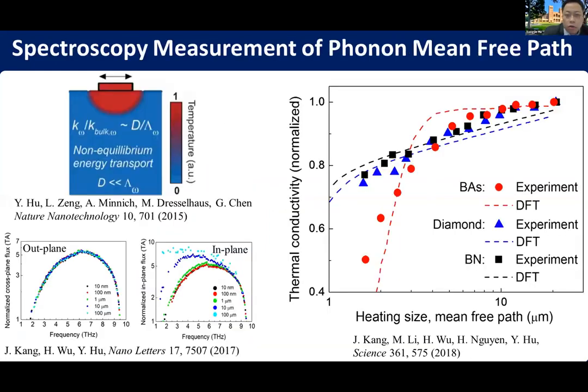We also performed spectroscopy measurement of phonon mean-free paths. So phonon mean-free path is a very important parameter that describes average distance for phonon to travel before it scatters. Usually, a longer phonon mean-free path would expect high thermal conductivity given other parameters are fixed. So I developed this spectroscopy technique with Gang. Essentially, we're using laser spot size, reducing the heating areas to probe the nanoscale ballistic thermal transport and measure the mean-free path. Later on, my group did careful examination by solving the 3-dimensional Boltzmann transport equation.